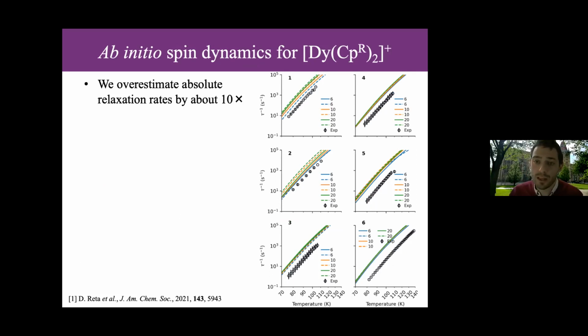And you can see the results here. So the black dots are the experimental Orbach relaxation rates, and the colored lines are different simulations. The solid lines include no calibration of the gas phase vibrational modes to the experimental ones, whereas the dotted lines include a calibration factor. So there's a very small change here. And the different numbers here relate to different line widths. So this is the line shape function that we're adding on the end.